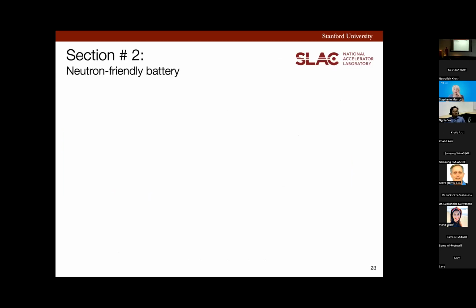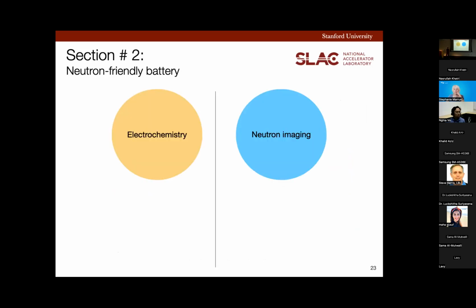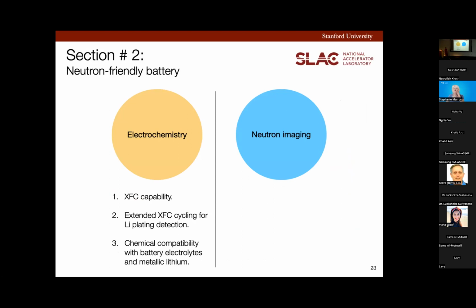Now, what is a neutron-friendly battery? This battery satisfies dual criteria from two scientific disciplines: first, electrochemistry, and second, neutron imaging. From the electrochemistry perspective, the battery should have XFC cycling capability. The battery should also be able to undergo extended XFC cycling so that I can detect lithium plating. And any chemical modifications I make in the battery should allow compatibility with the battery electrolytes and especially metallic lithium, because lithium is so reactive and we have to be safe.